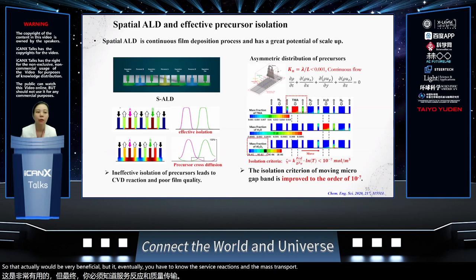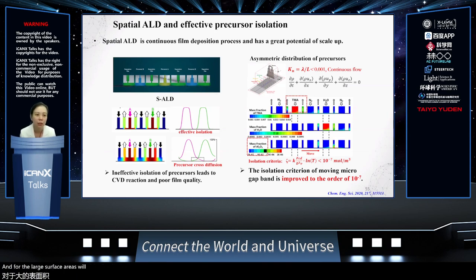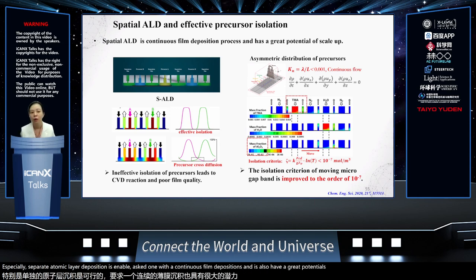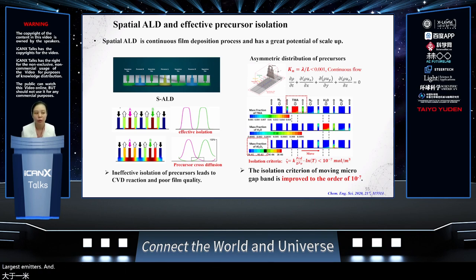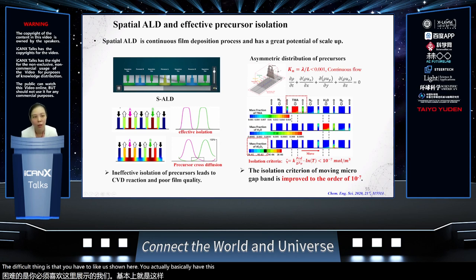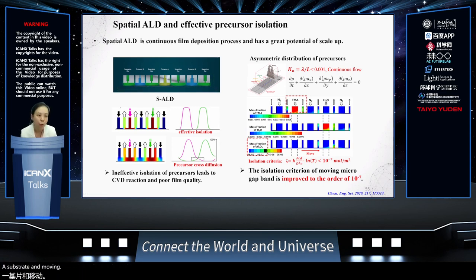there. And for the large surface areas, we run what we call spatially separated atomic layer deposition. It enables us to run continuous film depositions, and it also has great potential for larger than meter scales and continuous depositions. But for that, the difficult thing is that, as shown here, you basically have this substrate moving back and forth. You have very tiny gaps between the precursors and your substrate.